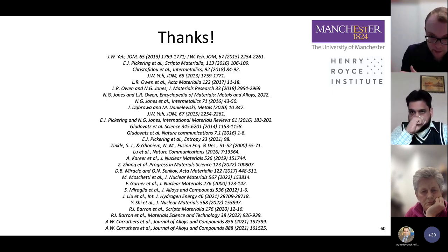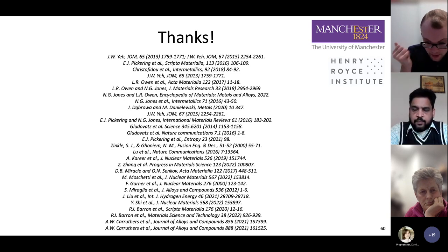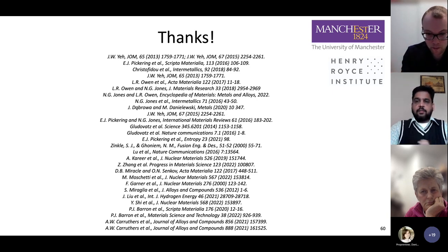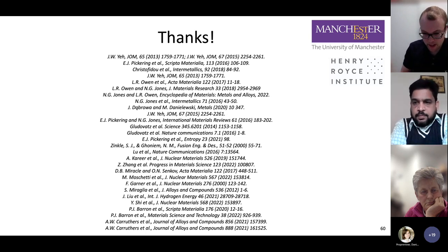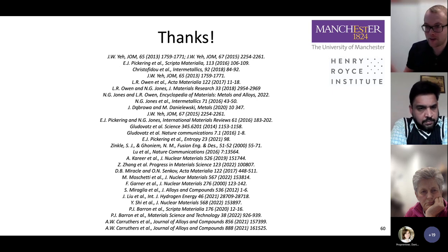But there are examples, and the interstitial one that you stated is a real critical one, where people have measured the properties of refractory high-entropy alloys and come up with different answers, of nominally the same compositions. And this is almost certainly due to changes in interstitial concentration.